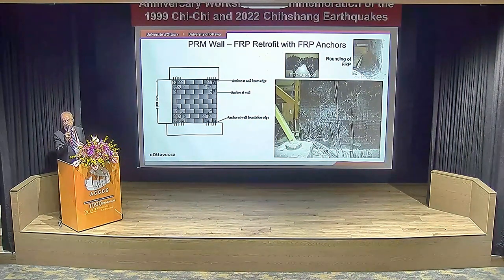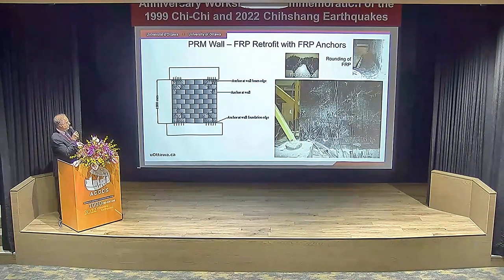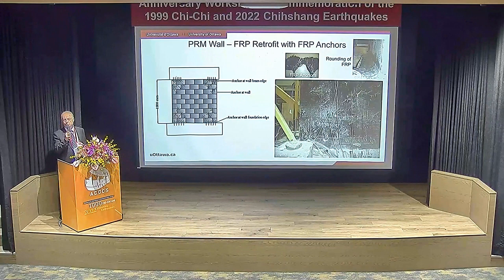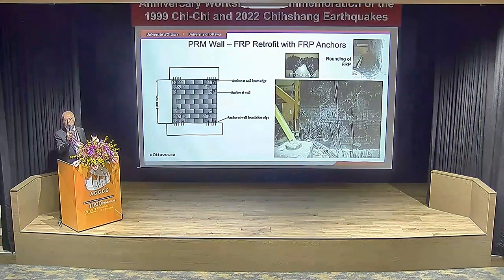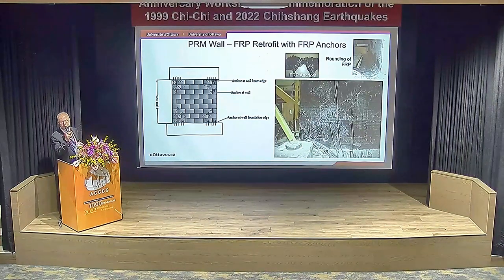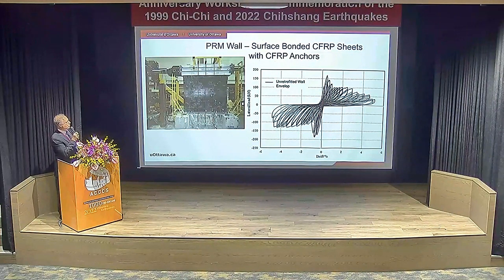We used homemade FRP anchors, so we anchored FRP to the foundation. That would be our longitudinal reinforcement, if you like, helping flexural capacity. And then there would be FRP anchors within the body, within the web of the wall, so that they would not delaminate and or debond, because we observed that at about 0.7% strain, FRP tends to delaminate, and we lose FRP. We had partial success in these tests. As you can see, red one is the control specimen, and there was some improvement in strength, but not a whole lot.